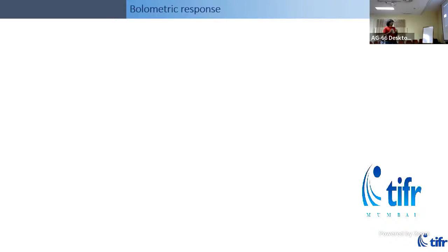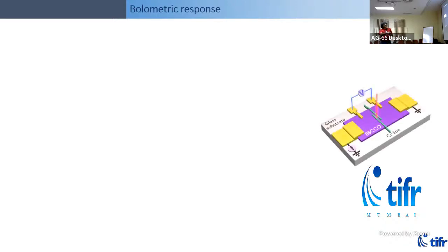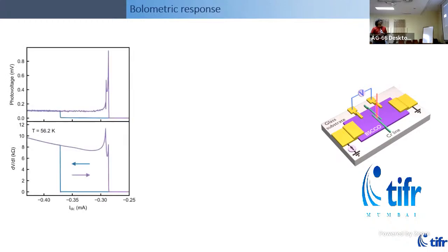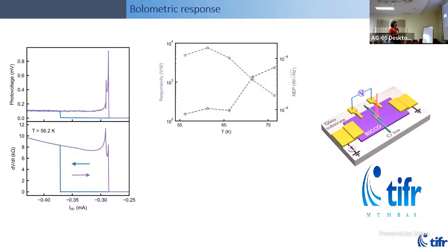Now, to study the bolometric response, we put this in an optical cryostat where we can shine a light using a laser of different wavelength and different power and different modulation frequency to test its limit. Eventually, you want to sense the photons that are coming in. We use sort of a supercontinuum source, but one of the big advantages of this kind of bolometric detection is that in principle it's very broadband, so it can go far into infrared if you design it. So besides the switching and retrapping physics that you'll see, if you measure the photovoltage, essentially voltage across the device as a response to the light shining on it, that also is pronounced as you bias it using different currents. And that's the mechanism for the bolometric response.